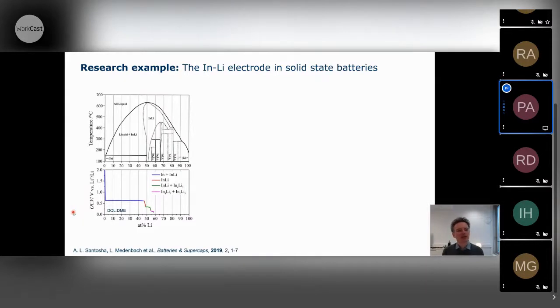And this is now all about a phase diagram. Phase diagrams always look very complex, but they contain very useful information. And what you see here is actually quite a nice example of how electrochemistry relates to phase diagrams. So this is a temperature axis. This is the phase diagram for indium, so pure indium on the left-hand side and pure lithium on the right-hand side. When you start lithiating indium, you start here and move this way through the phase diagram. You put more lithium in, and at some point you hit a line, and this means you have a phase transition. In this case, you form an intermetallic phase. Then again, you come into a two-phase region, and then you hit again an intermetallic phase, and so forth.